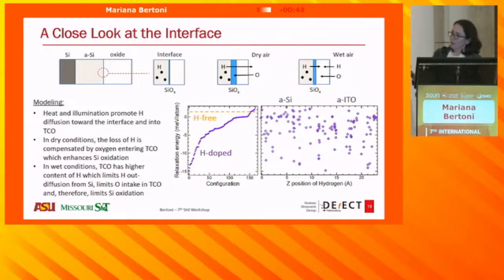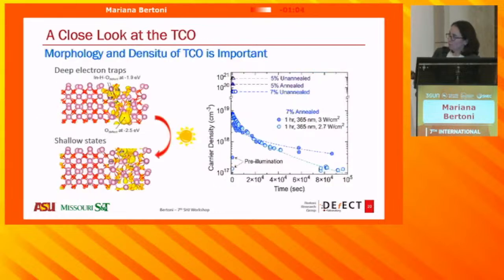So you end up having a thicker silicon, a thicker oxide, basically, at that interface. And I think hopefully Dana will show you some of those great results tomorrow. And in wet conditions, the TCO has a higher content of hydrogen, which limits basically the out diffusion of the hydrogen itself. All right.